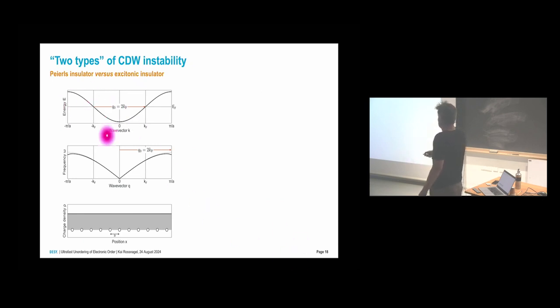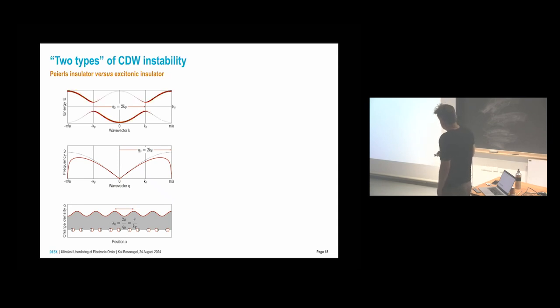And here is the simple picture of the Peierls instability. So again, parabolic band dispersion here in energy wave vector space, a phonon dispersion in frequency wave vector Q space, and here our lattice and the charge density wave. You have this perfect nesting of the two Fermi points, and you already see this here in this little softening of this mode here at the relevant wave vector. If you lower the temperature, this instability, you have a logarithmic divergence, and this drives your phonon soft. When you have a soft phonon, you have a static distortion, and if you have a static distortion in your electron density and in your lattice, this gives you a new periodicity, and then you have opening of the gap at the Fermi vector. Yeah, and then again, if this energy gain is sufficient, then all this is stabilized.